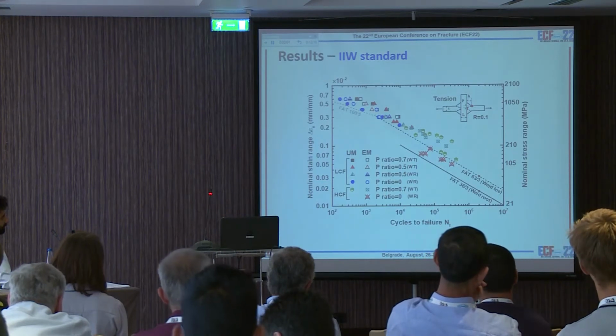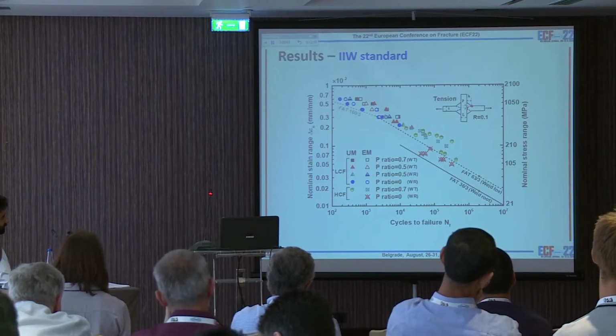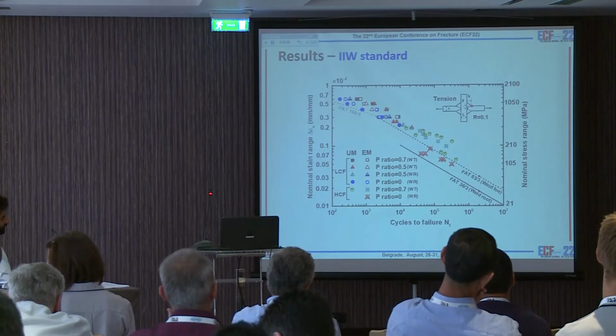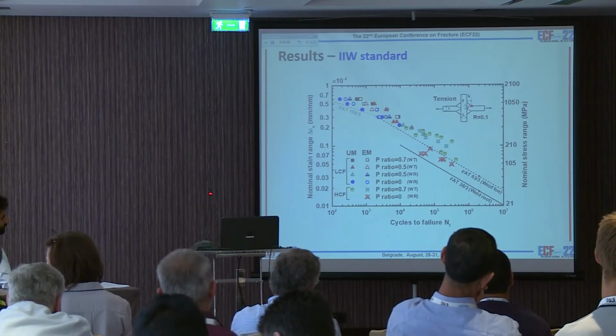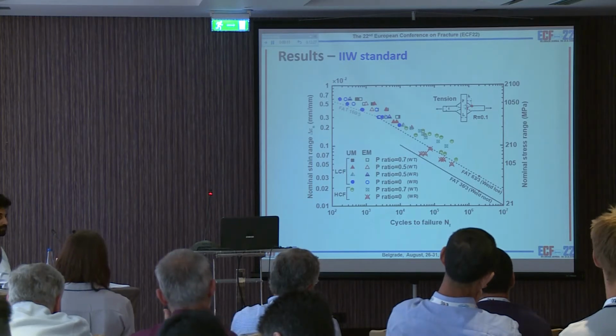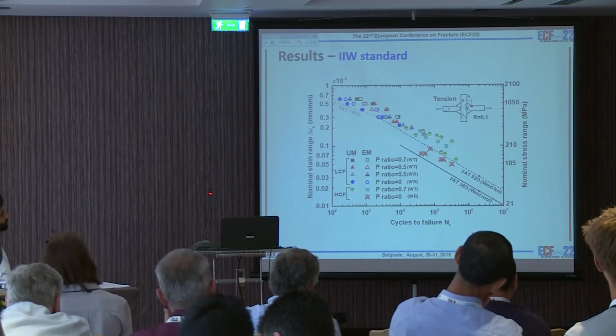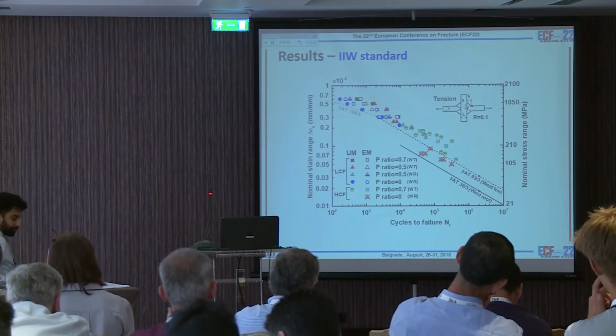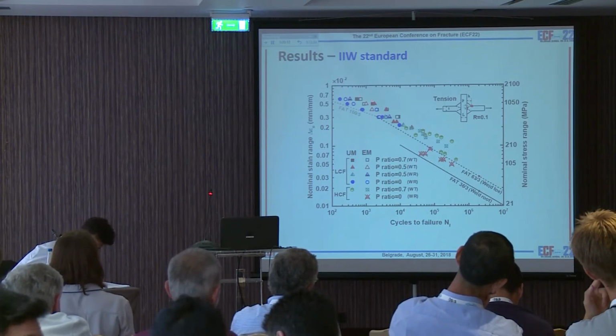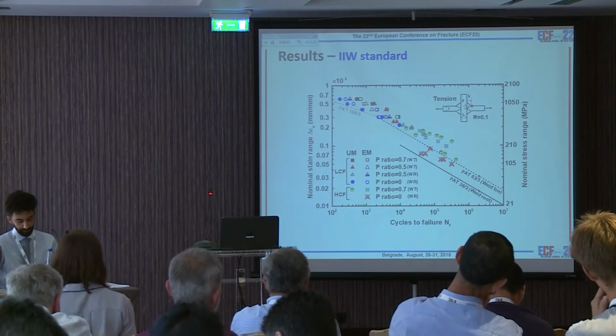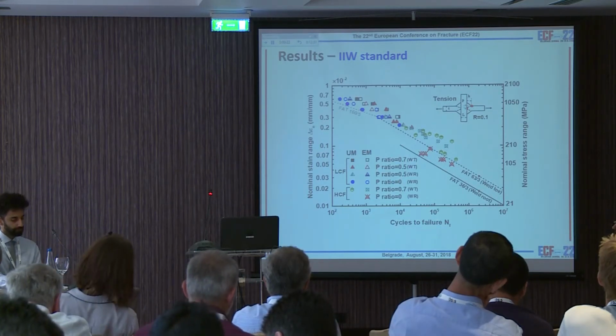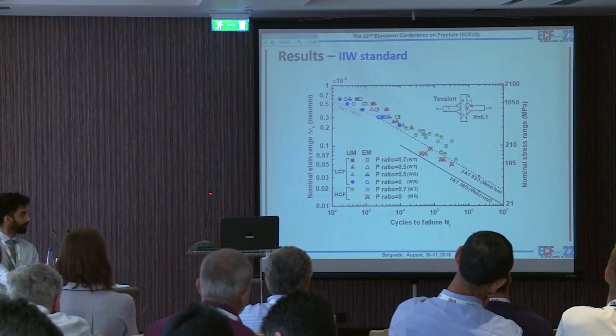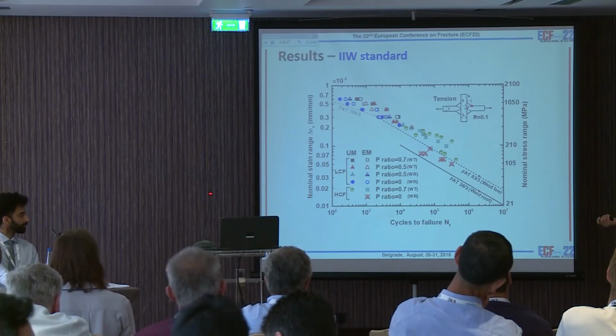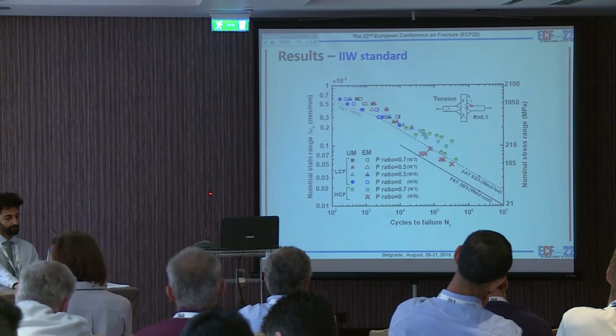So we put it together in the same diagram, and we can also find this for the low cycle fatigue. We could not find some standard in the IIW standard. So we try using the FAT 160 and the slope 4.5 for this joint failure. I think it's very suitable for the failure situation.